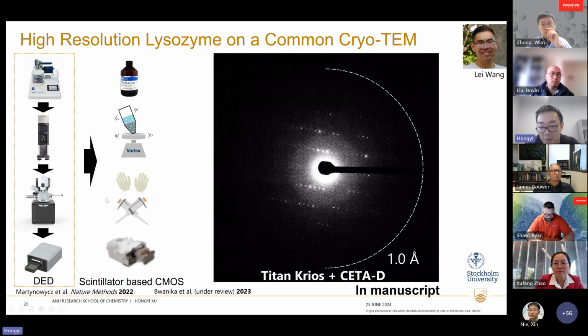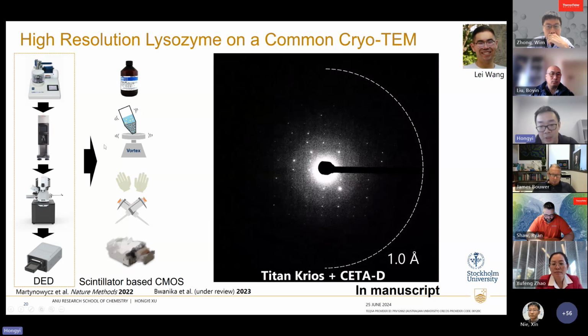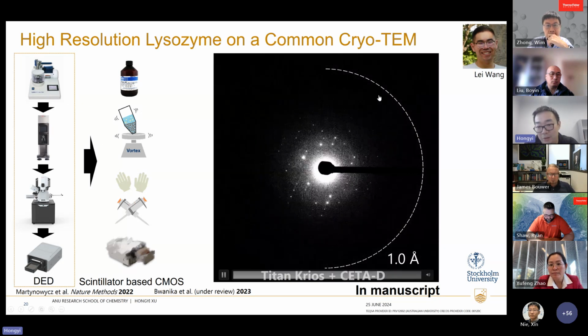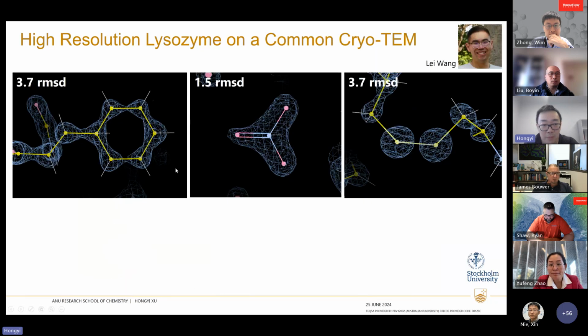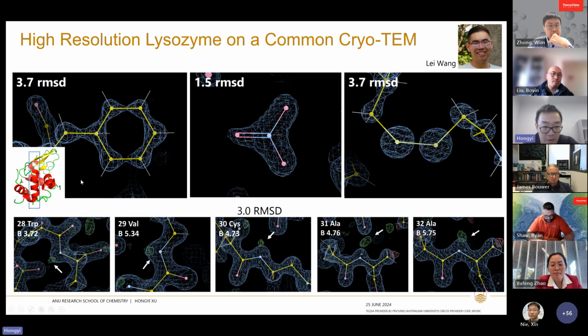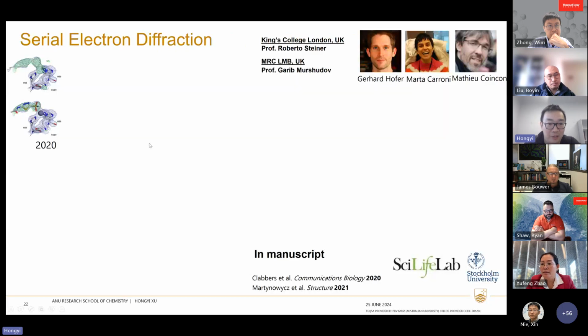So this is a Titan Krios with CETA-D. I think most of the cryo-EM labs should have this already, and then we can get to 1.0 angstrom resolution as well. And the map is actually slightly better than the published one. So if we look at the map, even the disulfide bridge, because we can merge a lot of data sets using AutoLEI, we don't see much damage even around the disulfide bond. And if we look at this alpha helix, we can see all the hydrogen signals coming out in the hydrogen bond.